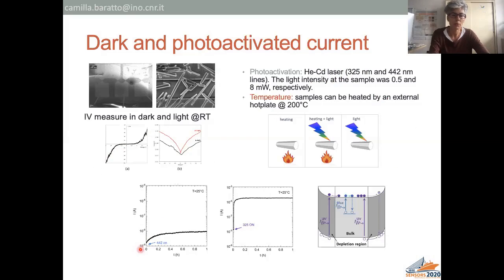And if you shine blue light, you have a small increase, by 1 order of magnitude, of the current flowing through the sensor in the humid air. Constant humid air was used during the measurement. And in case of UV light, you have an increase of 2 orders of magnitude, because super bandgap light can generate electron hole pairs that are available for reaction with what is on the surface. And indeed, an equilibrium condition was reached after oxygen photodesorption during the stabilization period.